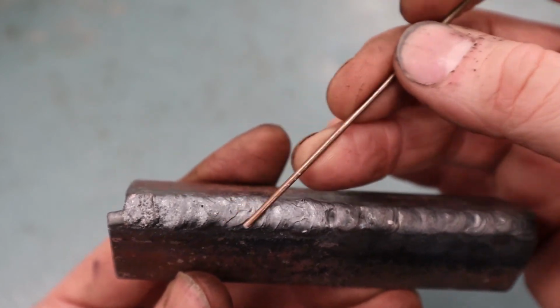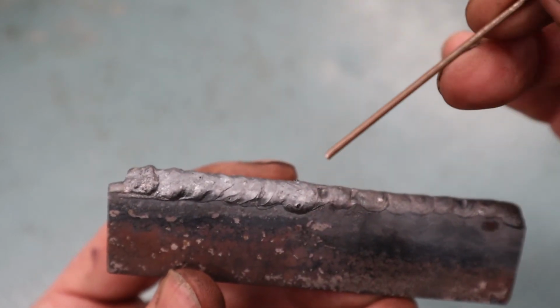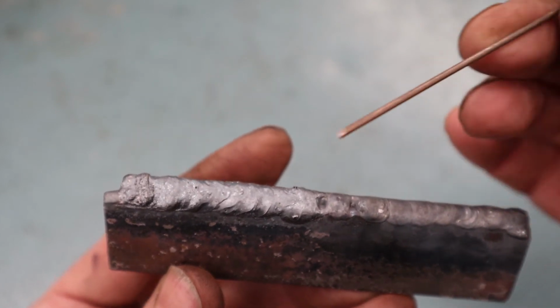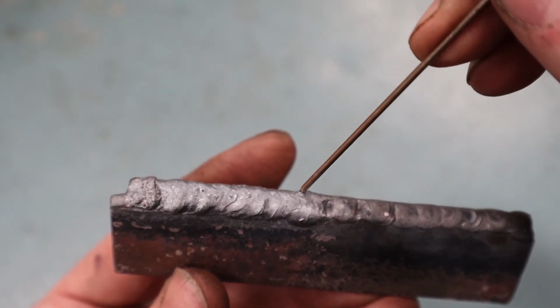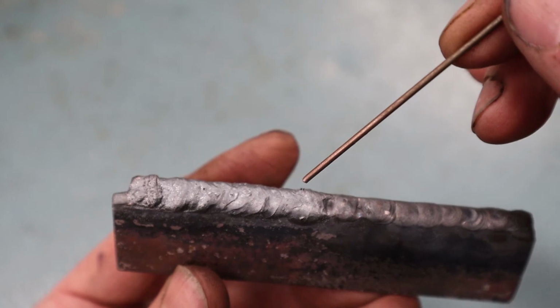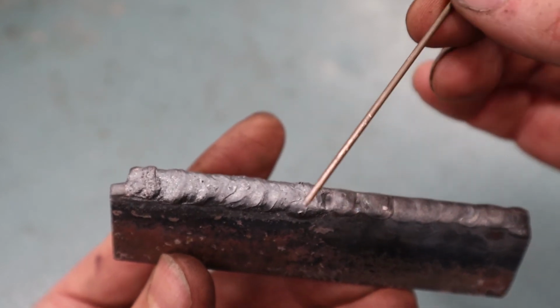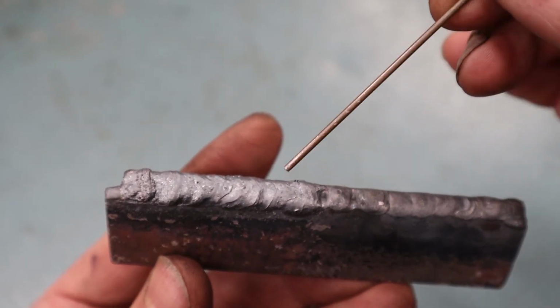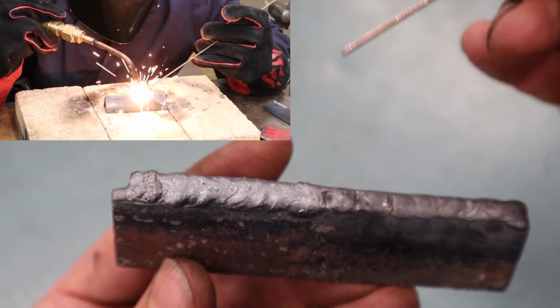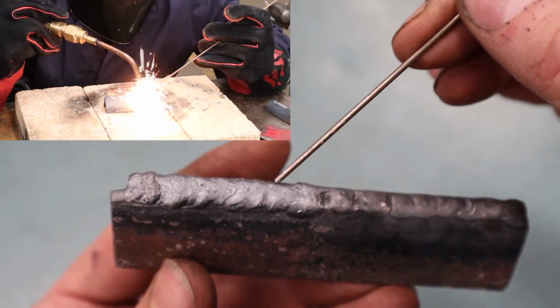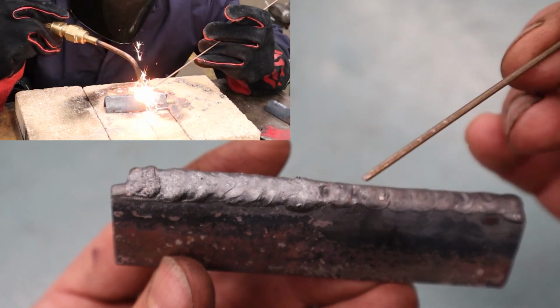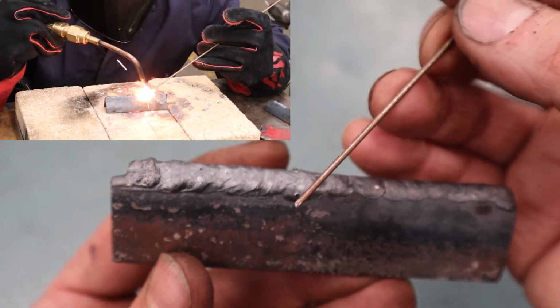It's kind of ashy and dull gray. That's going to tell us that we are either too hot, or in this case, the condition is that we were not welding with the neutral flame, we were welding with an oxidizing flame. So when I was welding this with the oxidizing flame, it was also sending off a ton of sparks and little twinkle things coming off of this. And that's another hint that something's wrong. It's either too hot or you've got an oxidizing flame.